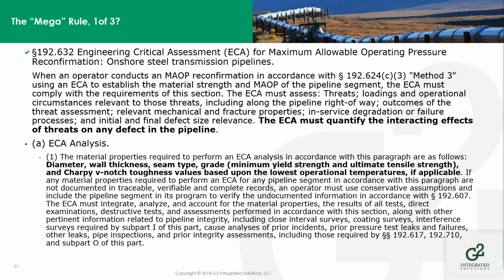The material properties in accordance with this paragraph have to be the diameter, the wall thickness, the seam type and grade, the Charpy V-notch toughness values based on the lowest operational temperatures as applicable. If any material properties required are not documented, traceable, verifiable, and complete, they have to be done so in accordance with 607. So you have to establish TVC records for this process to be followed.